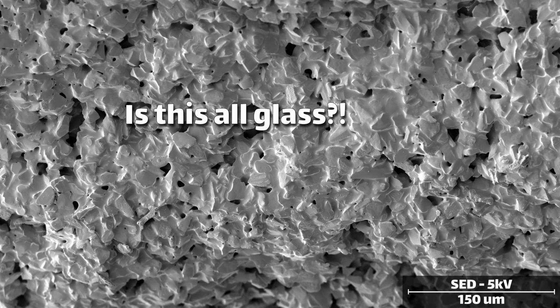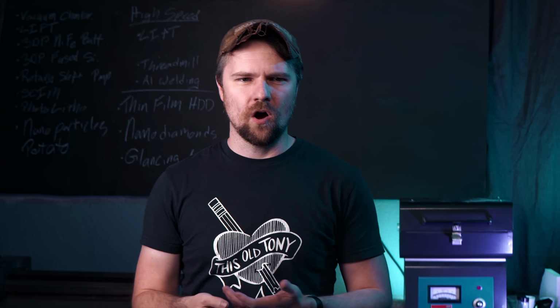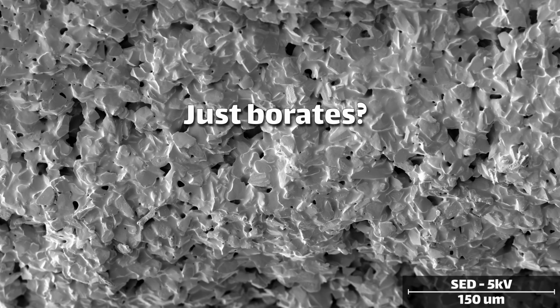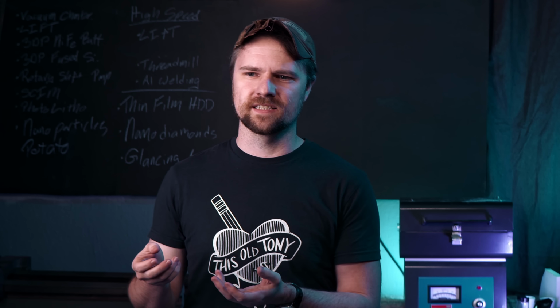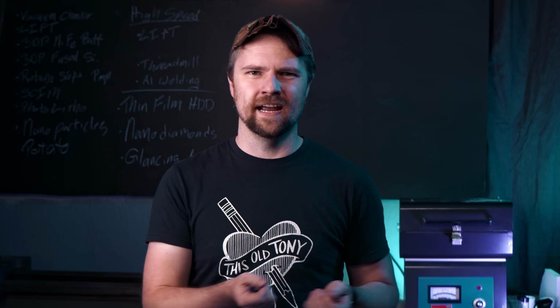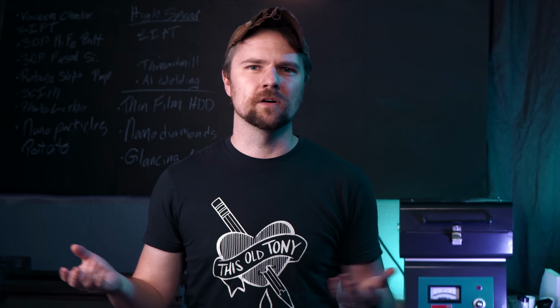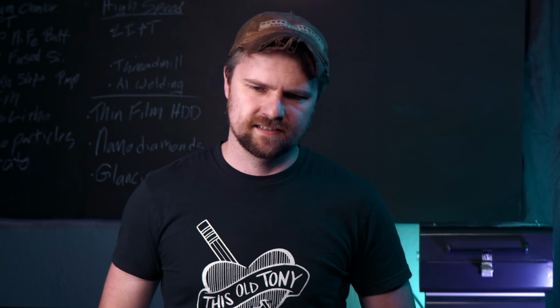And I started thinking about it more, and the borax doesn't go anywhere, right? It melts at a higher temperature, 750 if I remember correctly, and it's not being leached out in any way. So all of that borax is still sitting here. Is this thing that we're seeing actually just borax holding all the silicon carbide grains together? Like, is this sintering at all, or is it just a filler material, the carbide, with some borax glue around all the edges? So this caused some soul searching and existential angst, and questioning why I do this to myself.